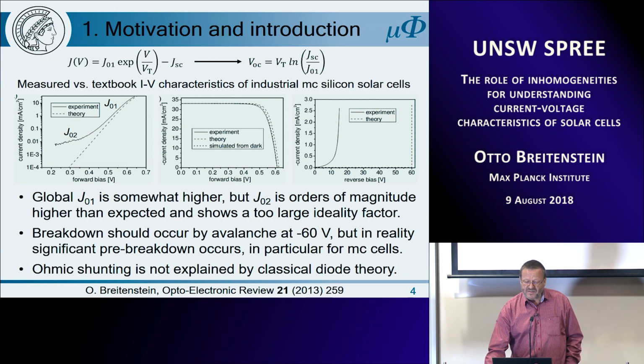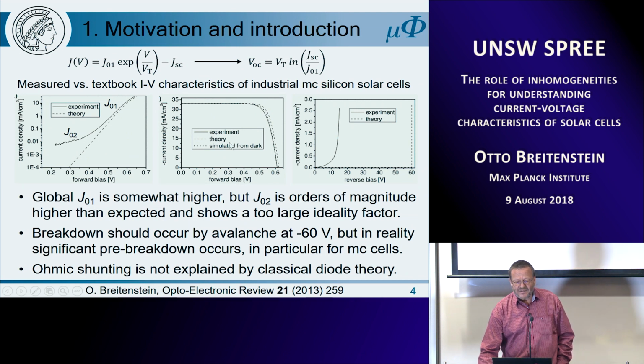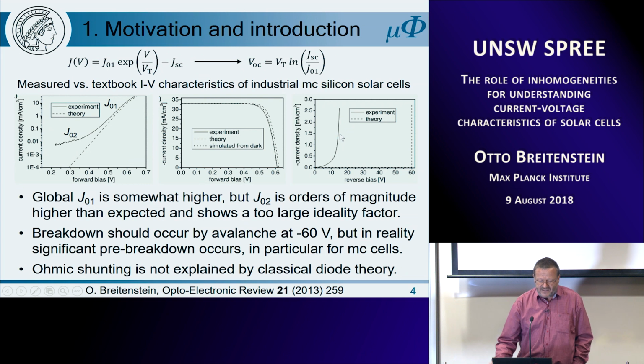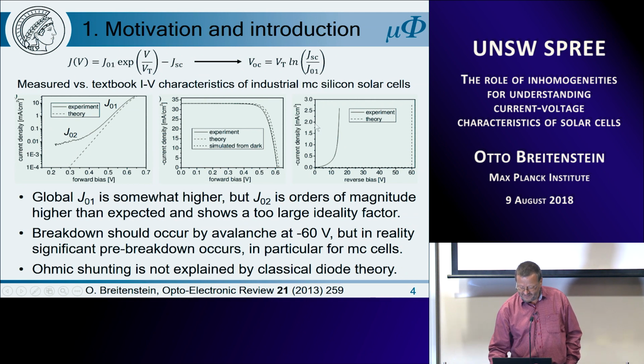And this also leads to some smaller differences in the illuminated characteristic. Theoretically we should expect a higher efficiency than in reality. And even if we simulate the illuminated characteristic from the dark one, including the series resistance, we do not get exactly the same, so we have some differences here. Another very strong difference is under reverse bias. We expect that a solar cell with a doping density of 10 to the 16 breaks down only at minus 60 volts, but in reality we have something like this. So these are strong deviations from the expected. The question is, where do they come from? And ohmic shunting is not explained by any classical diode theory.